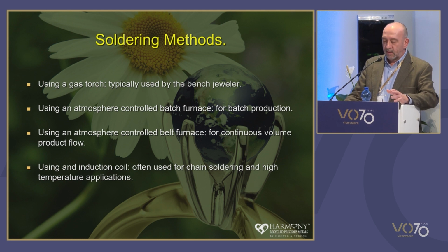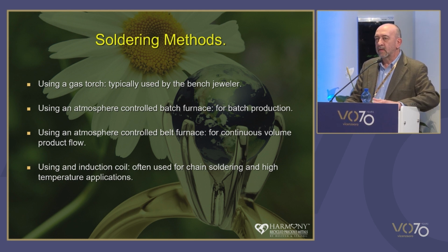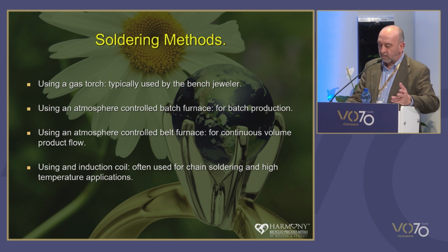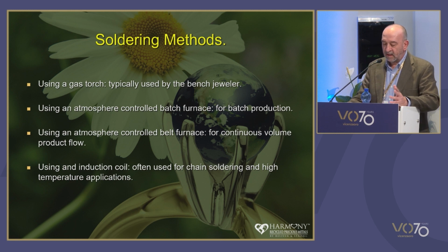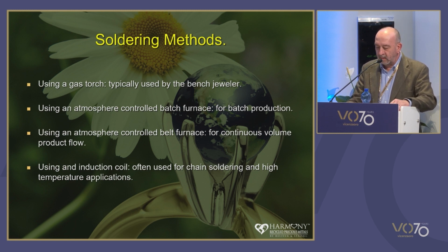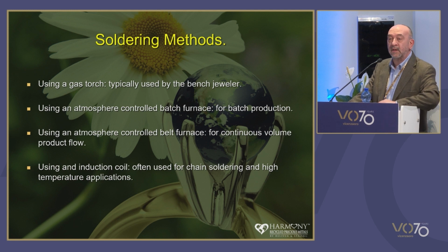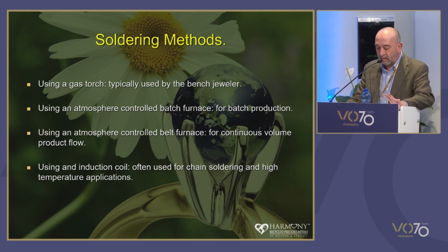So when torch soldering the joint, the area must be heated and not the solder. Everybody knows this who's a jeweler, but it's worth reiterating. Solders always flow to the area of greatest heat and not away from it, so that's how you do it. Time at temperature should be kept to a minimum to prevent excess flow and excessive diffusion into the parent metal or any volatilization of low melting point constituents from the solder, which can lead to porous joints. Both torch and furnace methods can use solder paste, but we're not going to go into these for this study. They're an entirely different study that could be looked at some point.